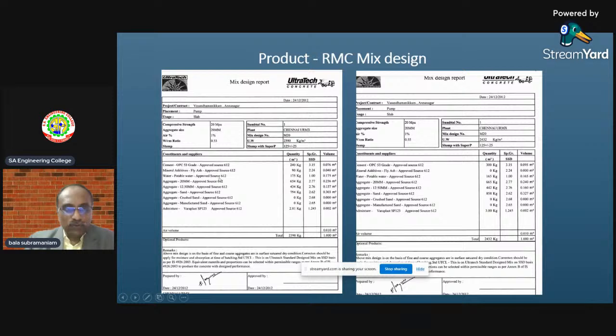Here they use 240 kg of cement, and we have a mineral additive, fly ash, of 90 kg, right? The ingredients are different. 240 kg of cement and 90 kg of fly ash. But the same strength has been achieved in the second, right-hand mixed design also. You see, there is no fly ash added here. You have only 300 kg of cement. This is OPC. So, for your understanding, the right-hand side mixed design shows a pure OPC cement mix, whereas the left-hand side is showing a PPC.